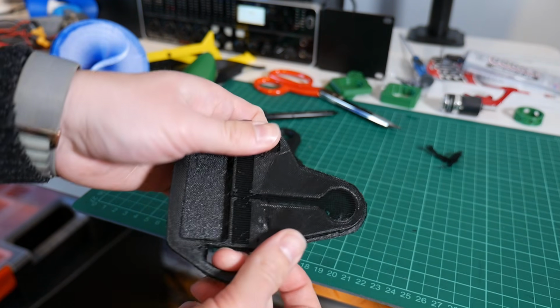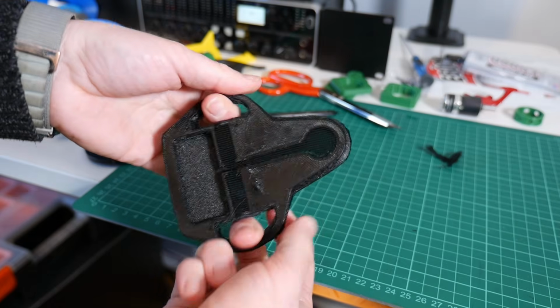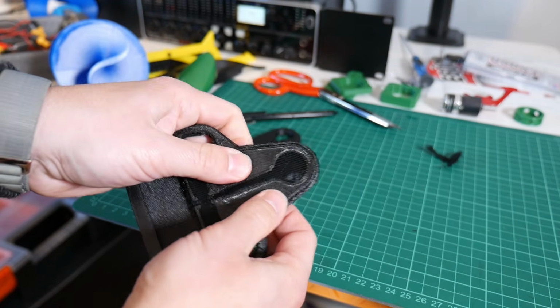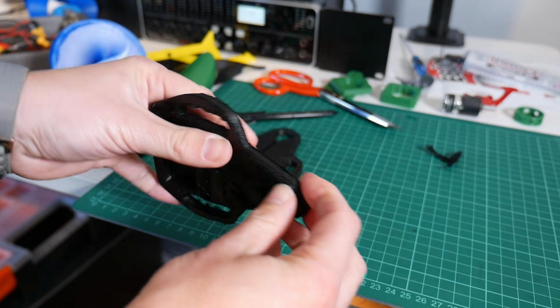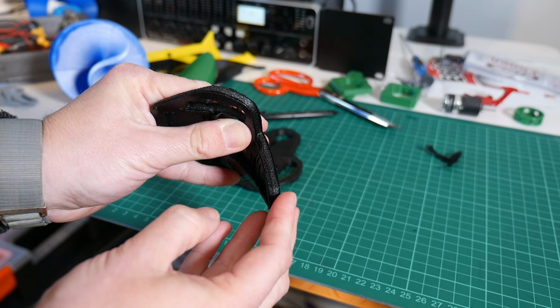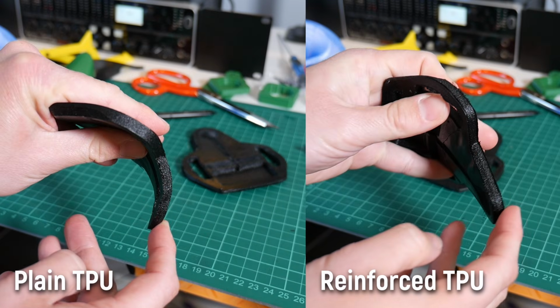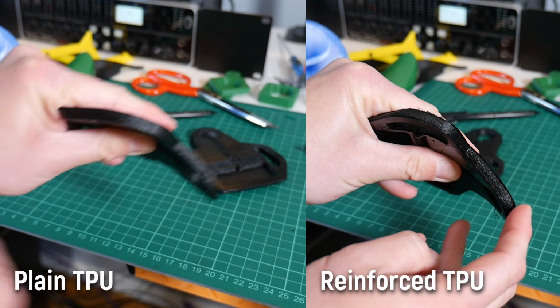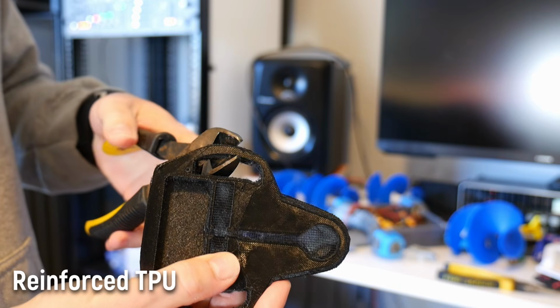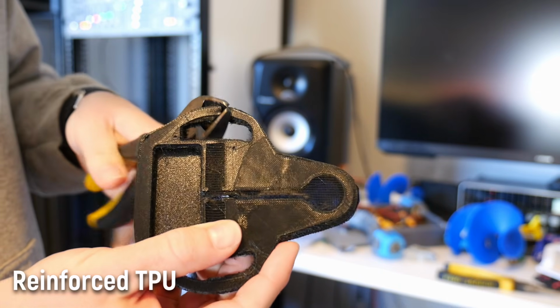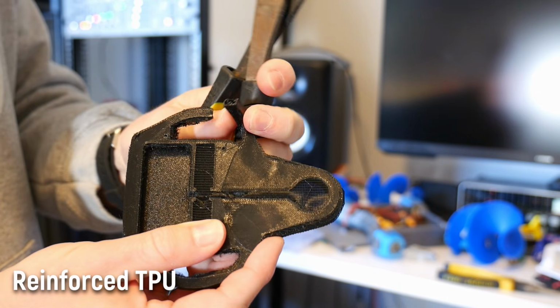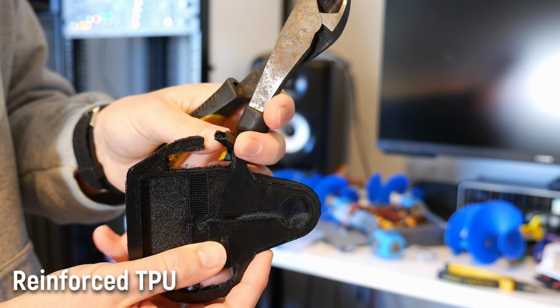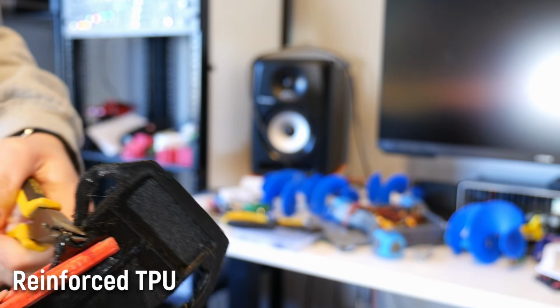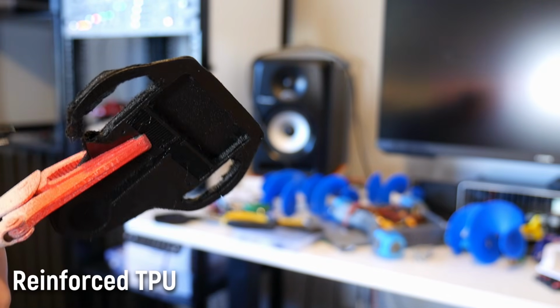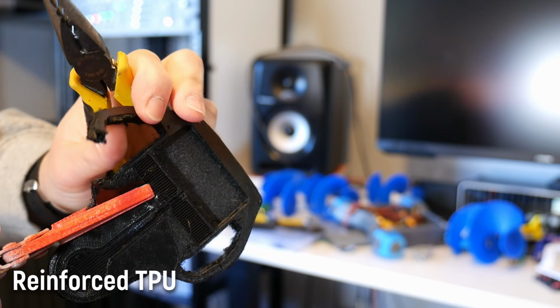However, after all of this effort, the results are somewhat underwhelming. The prints feel slightly different, with the reinforced print bending and buckling slightly less easily, but they both have the same degree of flexibility, and unfortunately it seems the same amount of resilience. A pair of side cutters made easy work through both prints. It was as if the nylon mesh wasn't even there, and I resorted to a brute force test to try tearing the print, and it just caused the nylon mesh to tear alongside the TPU.